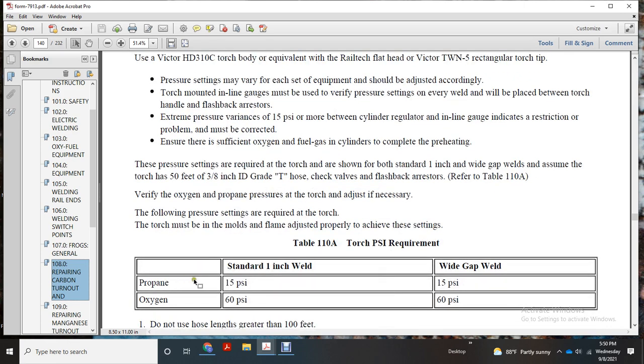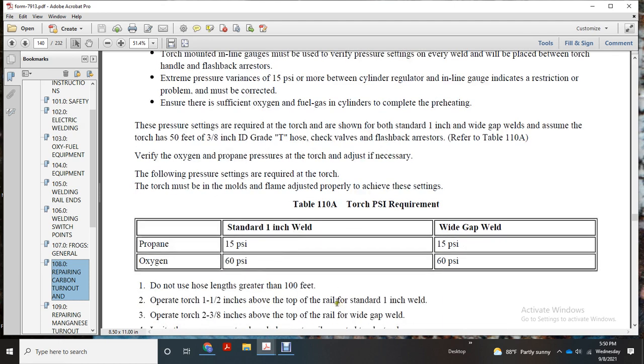Torch PSI requirements. Propane: 15 PSI for standard 1-inch weld, 15 PSI for wide gap weld. Oxygen: 60 PSI for standard 1-inch weld, 60 PSI for wide gap weld. Do not use a hose length greater than 100 feet. Operate the torch 1.5 inches above the top of the rail for the standard 1-inch weld, and 2 3/8 inches above the top of the rail for a wide gap weld.